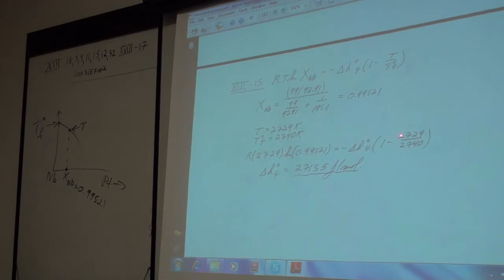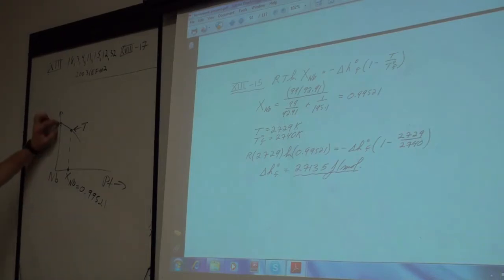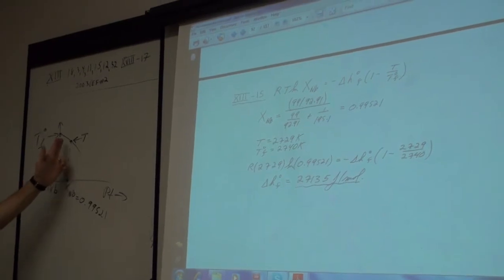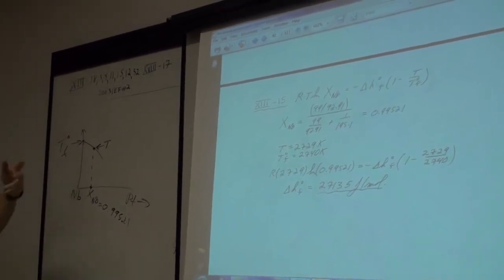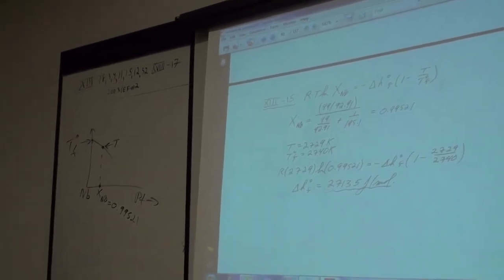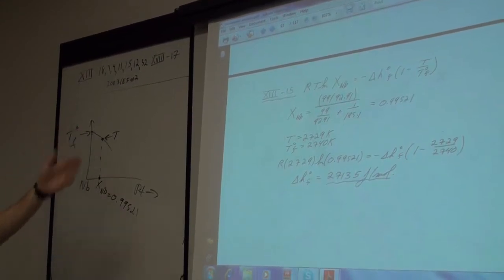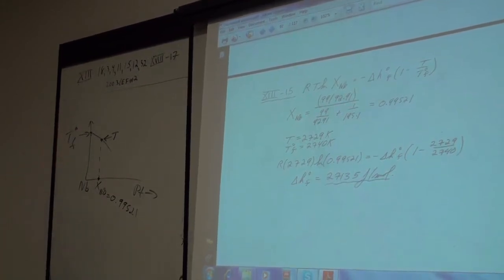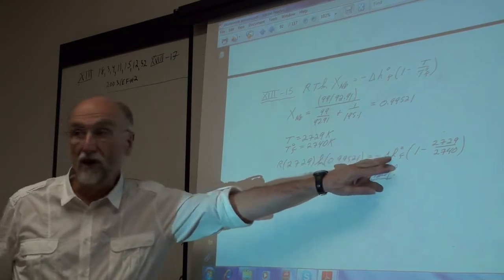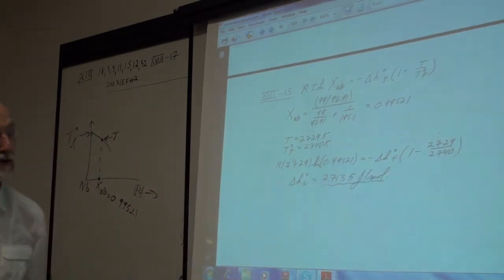I'm assuming, again, the heat of fusion is independent of temperature, but we're only talking about a very small temperature difference here, so as you get very, very close to this, this approximation really isn't a problem because you're taking the limiting slope. Or in other words, the heat of fusion is going to be pretty much constant over 11 degrees. And we've got to assume that there's no solubility of platinum in the solid niobium. Otherwise, you would have a minus RT log activity solid term here, which would be unknown.